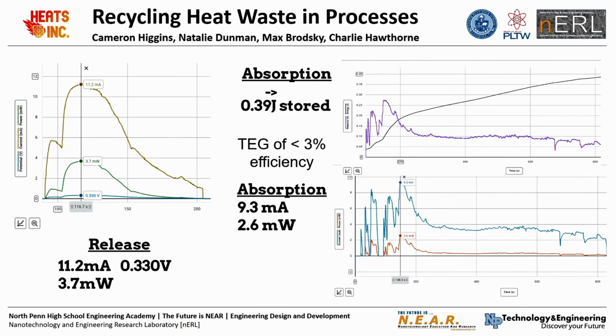From our results here, in 800 seconds, we were able to store 0.39 joules using the efficiency of the thermoelectric generator. And on the release, we were able to get a power output of 3.7 milliwatts. Now with a thermoelectric generator that is not commercial and higher end, like 12%, that would quadruple our results.